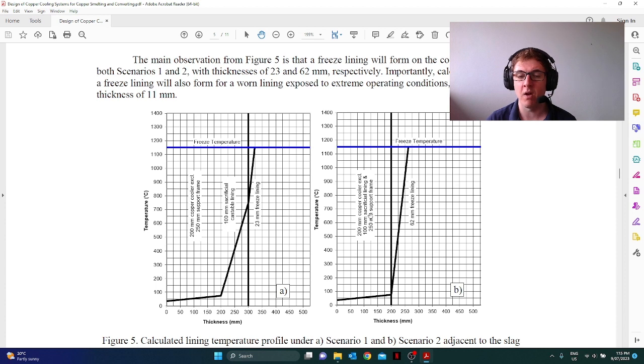They can be damaged for other reasons, but this is really neat because it shows that when you suck out enough heat and get to the point where the hot face temperature is below the freezing temperature, you form the freeze lining. But with just simple brick systems, you may not be able to do that by just adding water. So there's a sort of crossover point. You have to have either a refractory or a freeze lining. You can't really do a refractory with a freeze lining very easily at all.